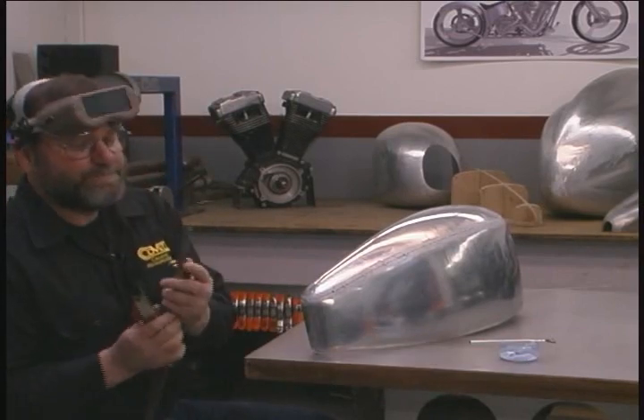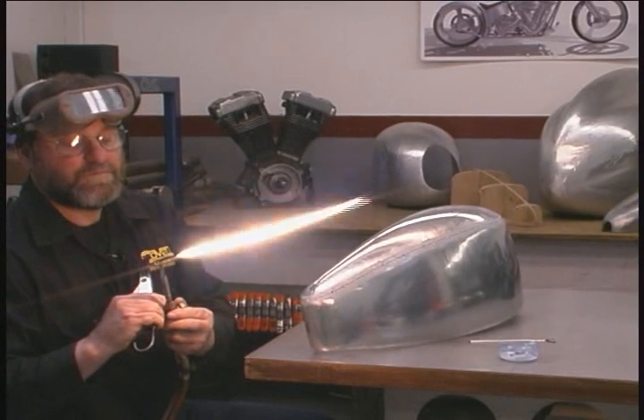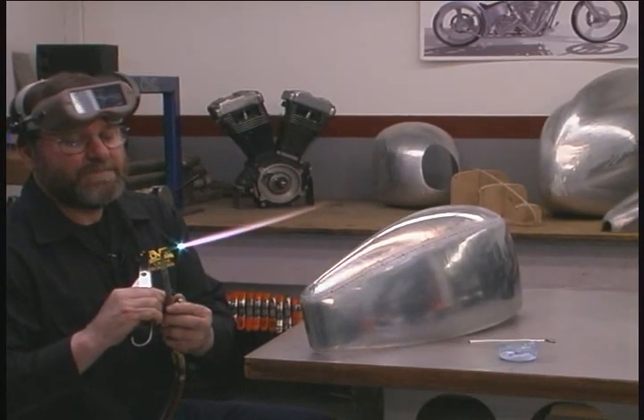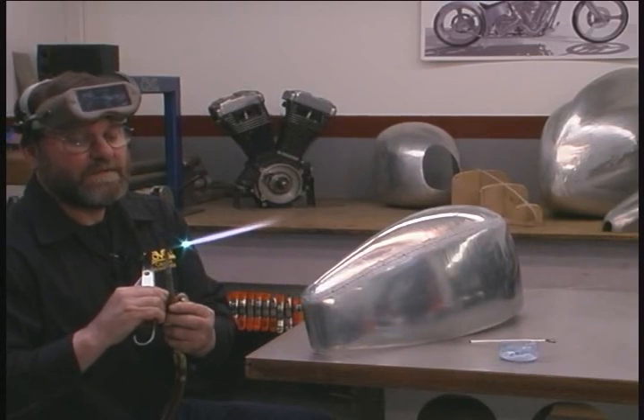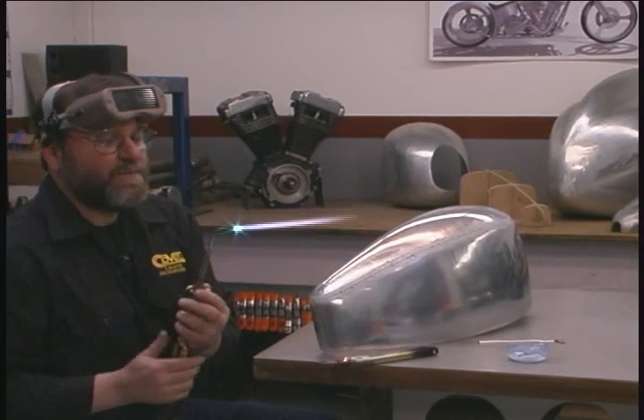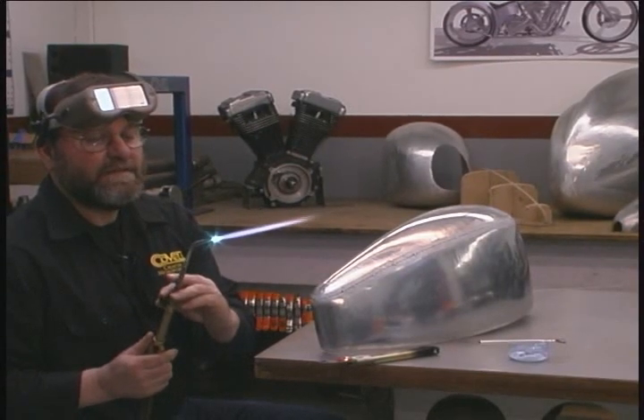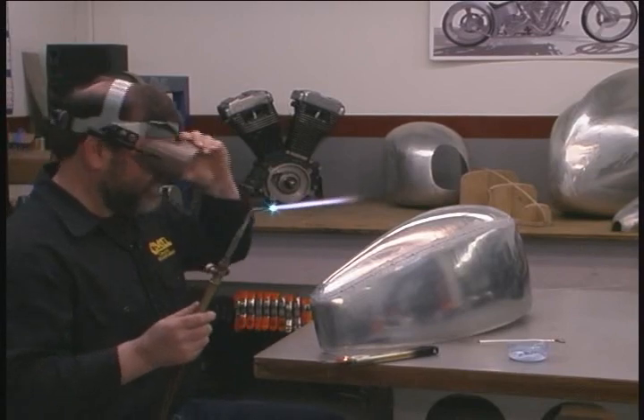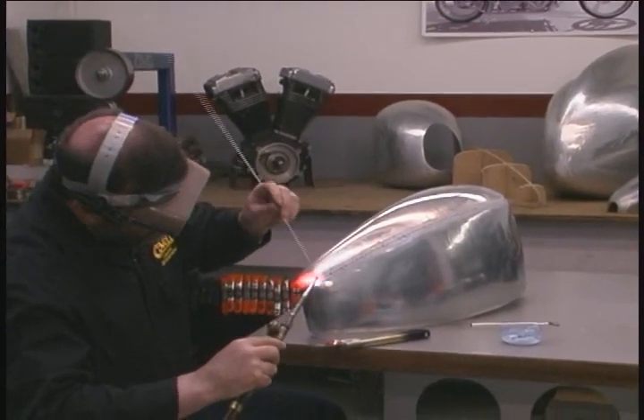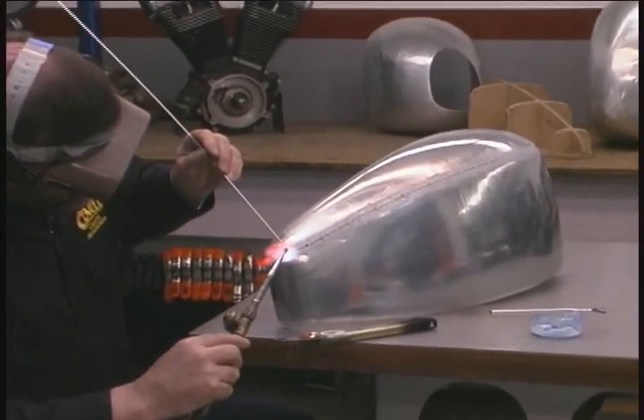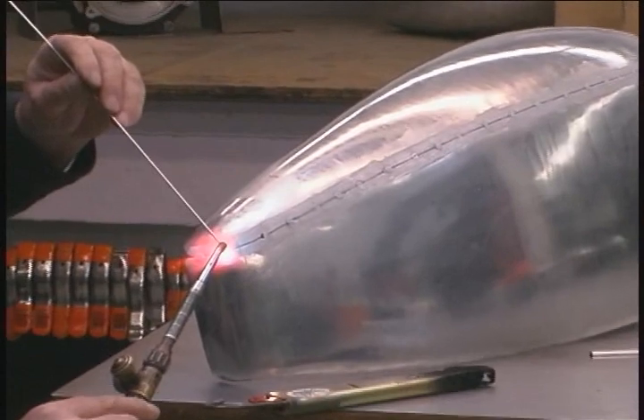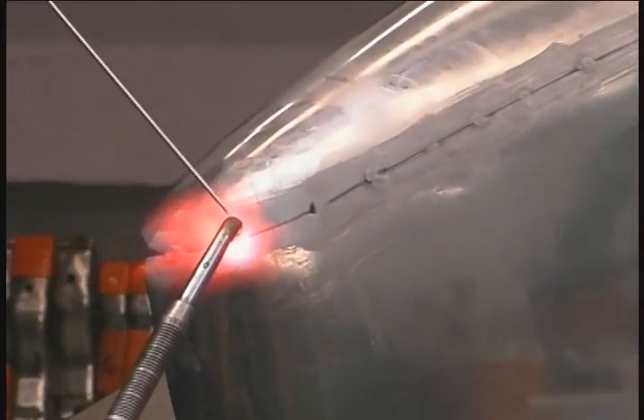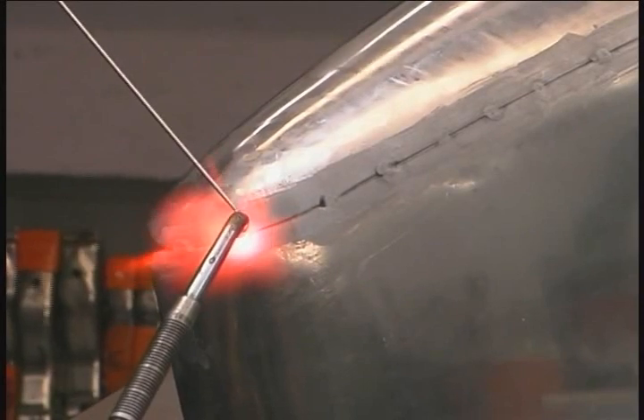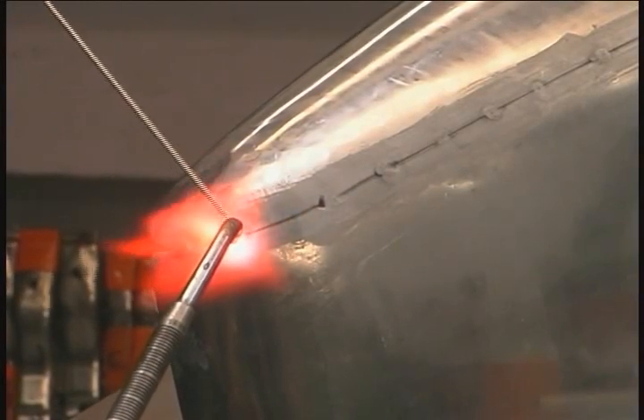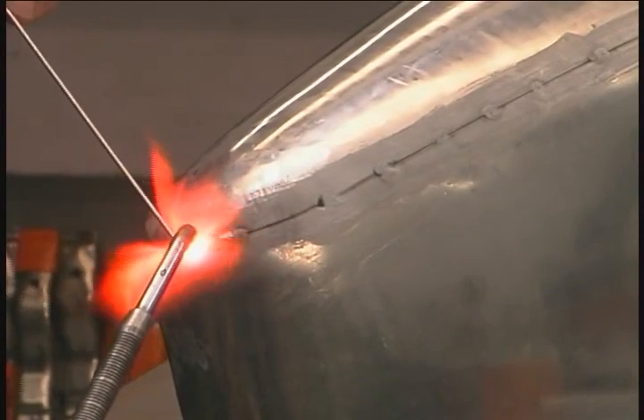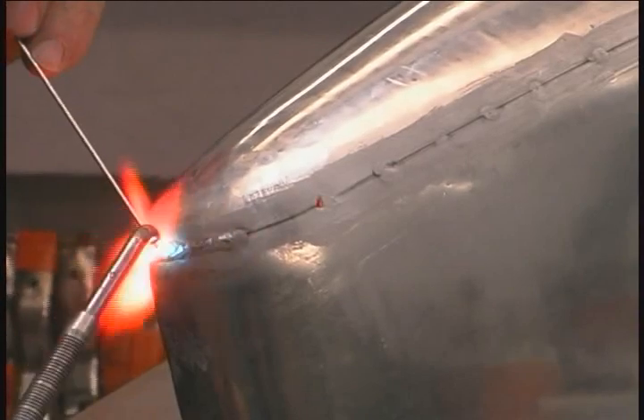So we'll light the torch. Use a neutral flame, medium-sized flame. And we'll start our weld, like I say, about 1 inch away from the end. Weld up to the end, then we'll stop. We're just waiting for a puddle to form. There's our puddle. Dip the rod in and weld to the end.